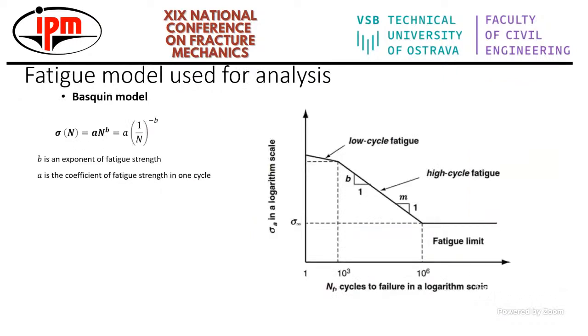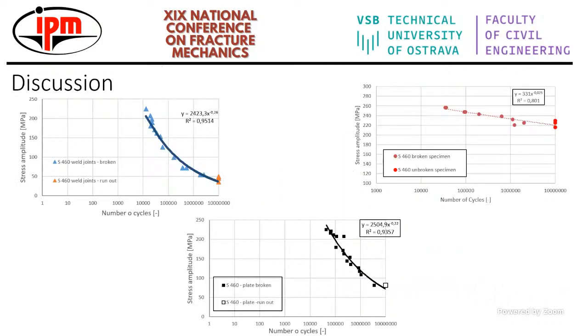Okay, then as you saw the results, we have to quantify them. The first is very easy. It was by the Basquin model. It was not necessary to show it. Theoretically it is good to show it in log scale, but in my case I use log information on the x-axis and the standard one, so the semi-logarithmic axis, for comparison of the results. Then you can see that when we use the cruciform or the plate, the index of dispersion is almost better than for the pure material.